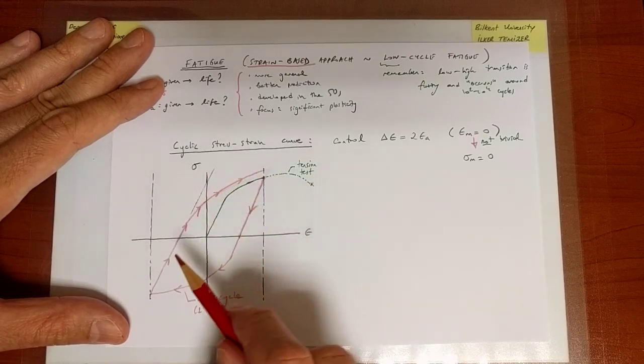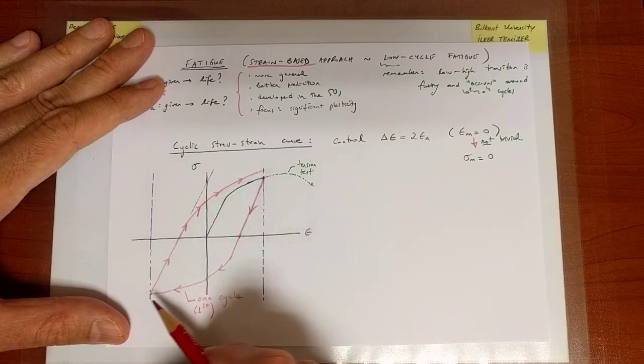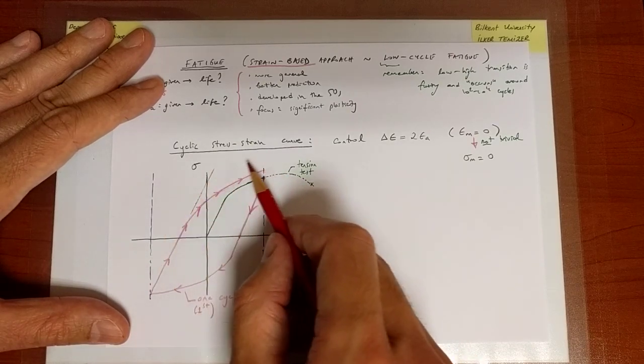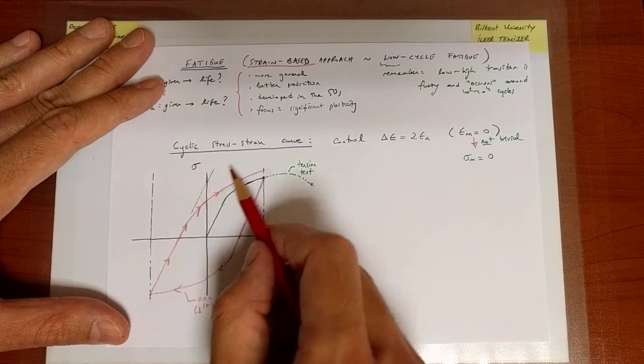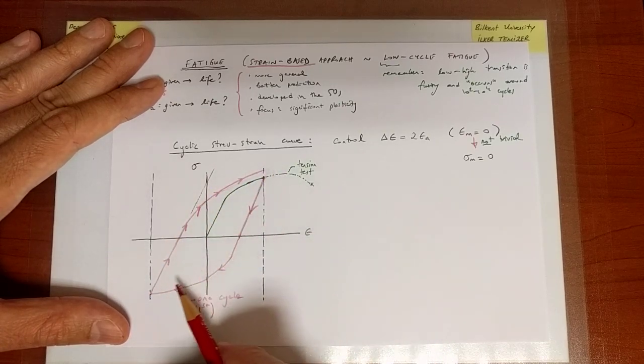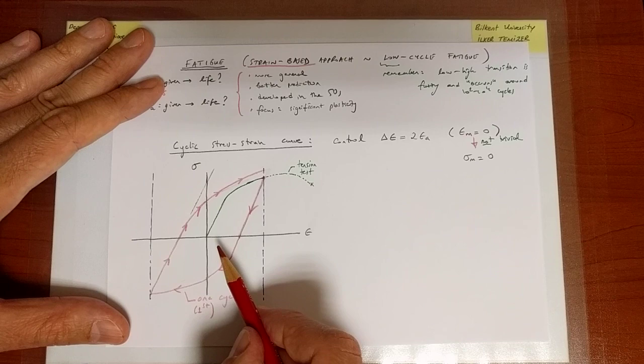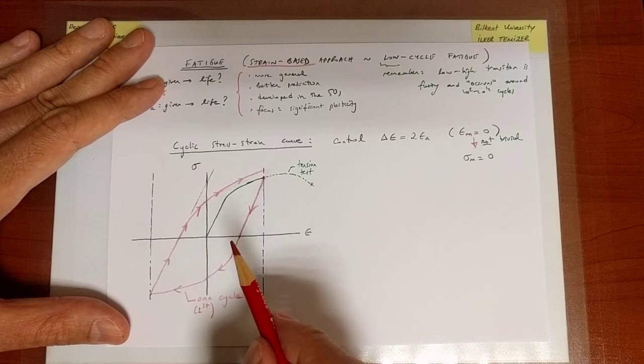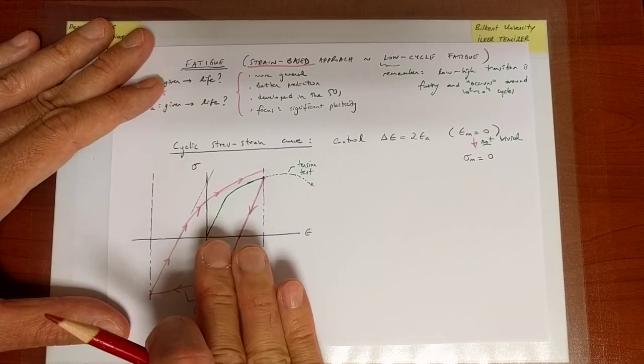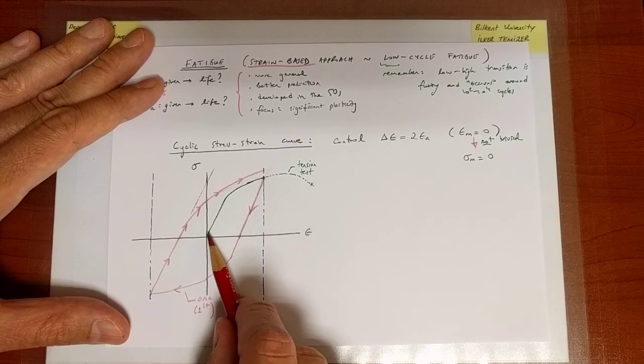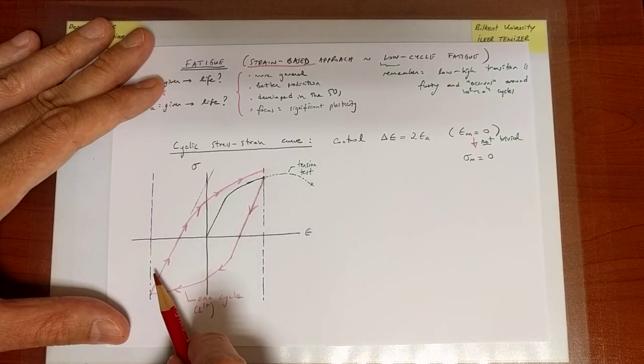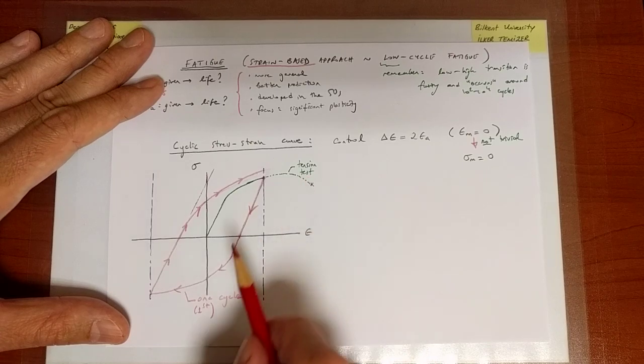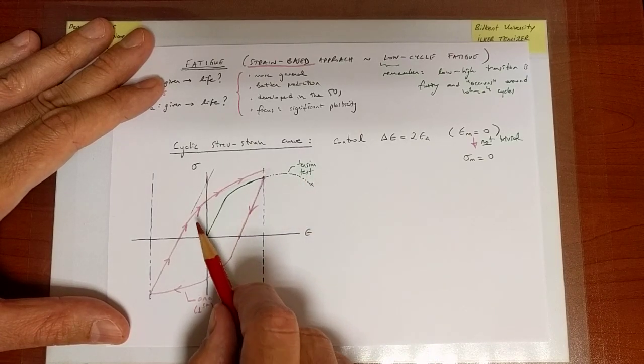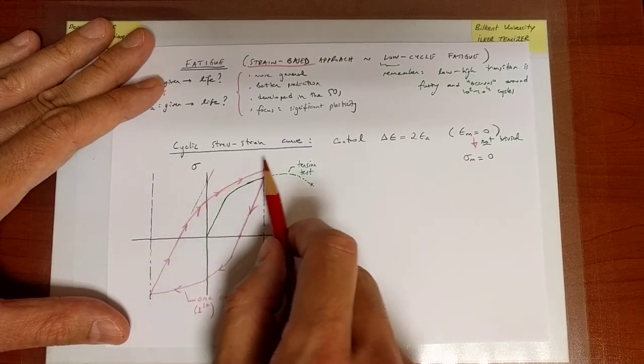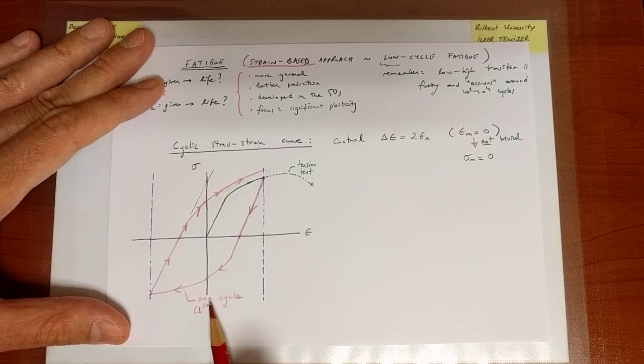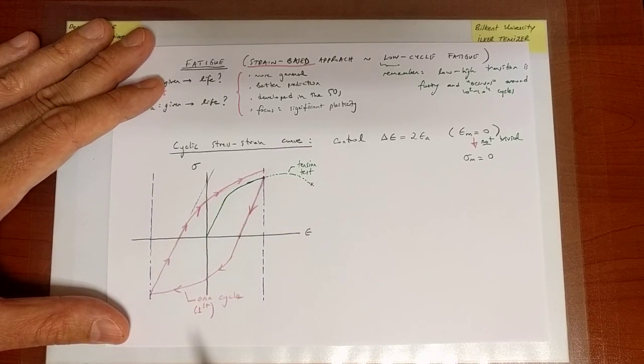But it turns out that if we do this enough number of times, then that cycle starts to follow a closed path, which we are going to call the cyclic stress-strain curve or the stable hysteresis loop. So we're going to draw that next. But presently what we've observed is that even the first cycle differs significantly from the uniaxial tension test stress-strain curve, and every other cycle eventually will differ from the previous cycle stress-strain curve to some extent.